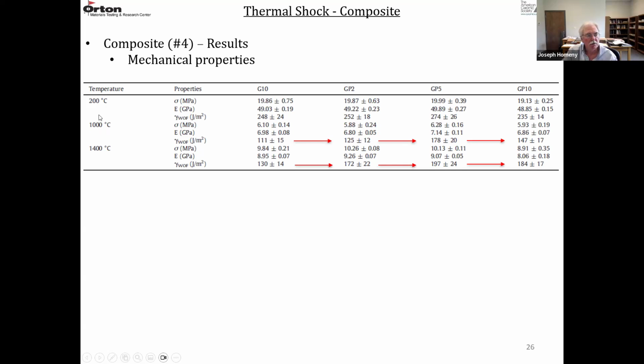So these are the properties after 200, 1000, and 1400 degrees C curing: the strength, the elastic modulus, and the work of fracture. If you look at the strength at 200, this is G10, no additional pellets, and GP2, GP5, and GP10. The strengths are all about the same, 19 megapascals. The elastic modulus is about the same, 49 gigapascals. And then the work of fracture, they're all pretty similar, about 250 plus or minus maybe 20. So maybe 250 joules per meter squared.